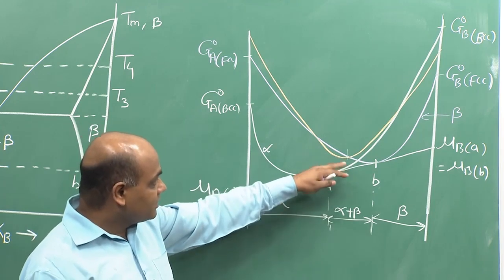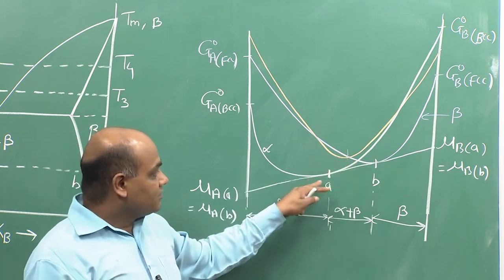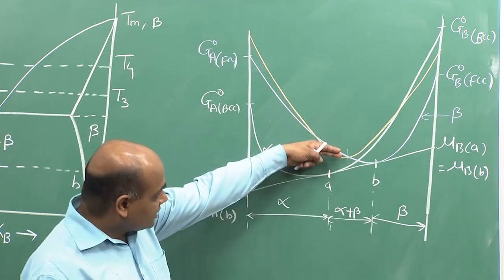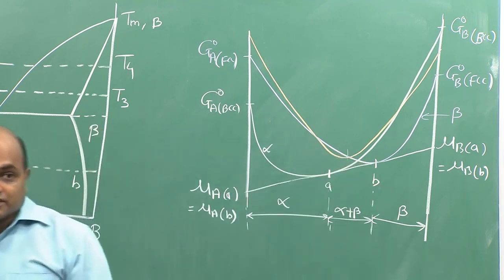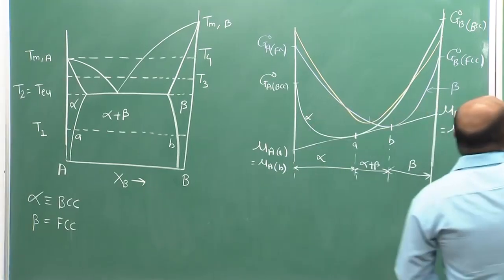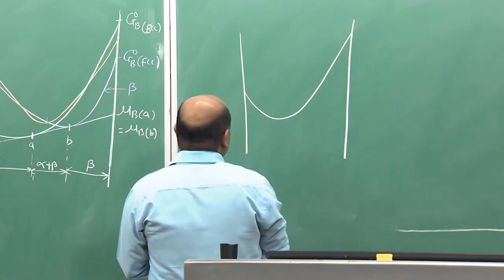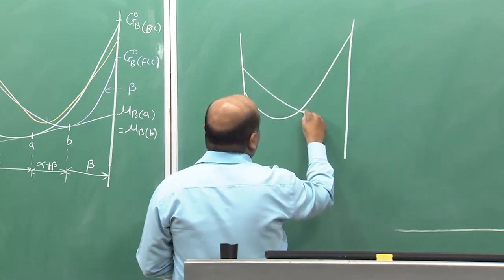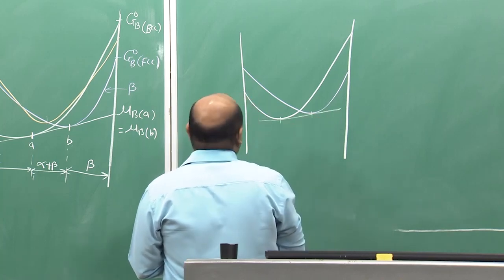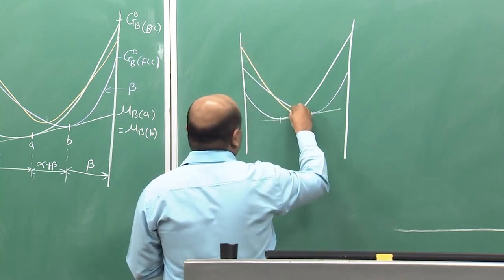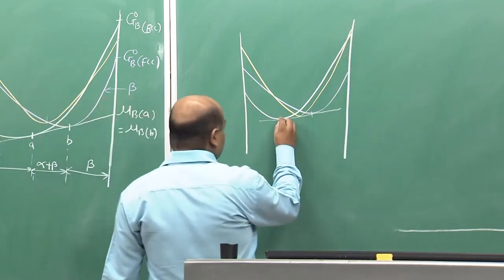So, at one point you can imagine, the temperature will come when there may be a possibility that there will be a triple tangent, because this liquid curve relatively is shifting down. So, at some point it may touch the common tangent to both the solid solutions, right. So, in that case, there is a common tangent and the liquid is also touching. So, there is basically a three phase equilibrium,